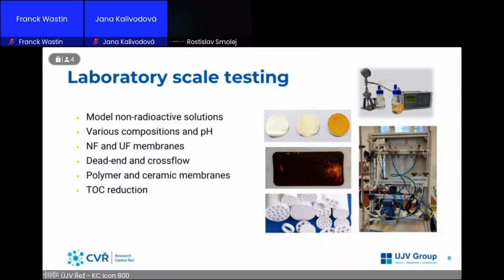For those who are not really familiar with dead-end and cross-flow setting, the cross-flow setting has 2 streams. One is the permeate, and then the concentrate, where the blocked compounds are concentrated, and the dead-end is classic filtration, like your morning cup of coffee, for example. And then we also, because of the membrane durability, we tested the polymer membrane and the ceramic membranes as well. In this step, we looked into the total organic carbon reduction as well as a pre-treatment, because the liquid radioactive waste always have some complexing agents which are used for decontamination, or some surfactants which are used in the laundry or drainage cleans and similar.